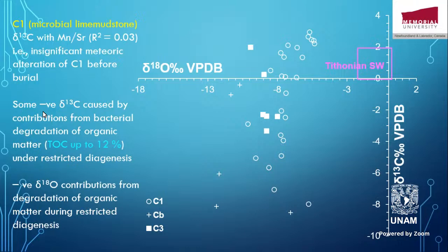And also, there are some negative delta carbon 13 values here. You can see them very negative for C1, which is the lime mudstone. This is likely due to contributions from the bacterial degradation of organic matter that released lots of carbon dioxide, and even minor alteration or recrystallization of that lime mud with lots of carbon dioxide coming from the degradation of organic matter can cause significant depletion in the delta value. As you can see here, it's below -4, -6, -8. That's too much for the lime mudstone. It means that there was organic matter involved in this.